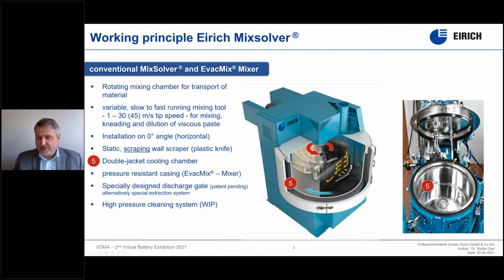The lithium-ion battery industry forced us to introduce a double-jacket cooling system. It was not necessary for almost 100 years. So today we are offering machines with a double-jacket cooling system, which rotates together with the mixing chamber. It is directly connected, and the liquids which have to be introduced into a rotating system are charged with a special transfer system. We can put the complete interior mixing chamber, with the same design and same tools, into a pressure vessel, which allows us to operate the machine under pressure and vacuum for superior degassing of the coating slurry.